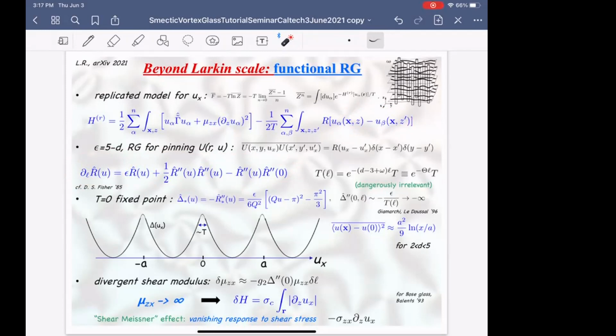They're all equally relevant because the temperature is irrelevant below 5 dimensions, or above, I should say, above 2 plus epsilon dimensions. And because temperature goes to 0, it's a dangerously irrelevant variable. All the harmonics of this random potential are equally relevant, and so one has to study a whole function, and hence functional RG. It's controlled by epsilon expansion around 5 dimensions.